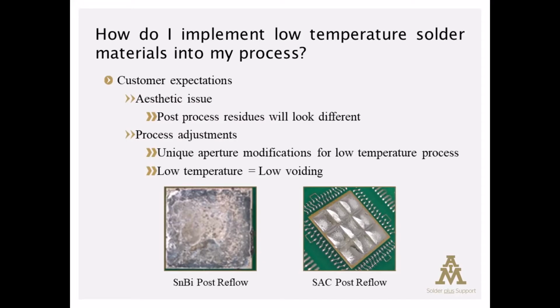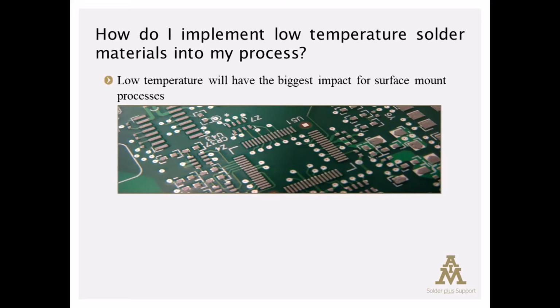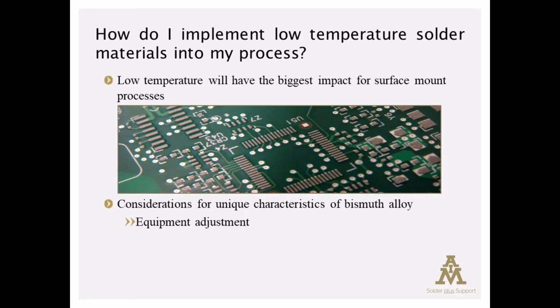You know, the low temperature revolution is going to take place at surface mount first, and then may find its way into wave soldering. One of the interesting things about low temperature materials being primarily high bismuth materials is that bismuth is like liquid water in that when it freezes, it becomes less dense as a solid, like an ice cube floats in a drink as a solid. And in most materials, the solid is more dense than the liquid and sinks. Bismuth and water share that in common. So we'll have to take into consideration the effect of that on the equipment. There may be some solder pots that have to be reconfigured or redesigned or are incompatible with that characteristic of high bismuth materials when used in wave soldering.